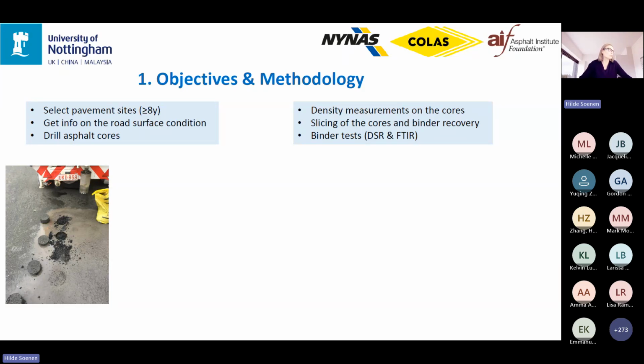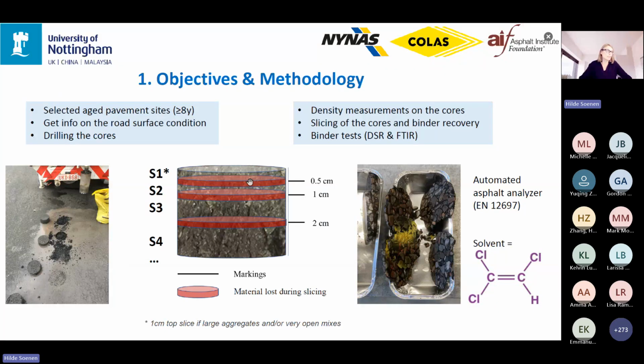Once we had enough cores, density measurements were conducted, nuclear density, which has the advantage that you get a density number every millimeter. After that, we sliced the cores. In this case, you can see we used very thin slices. First, we put markings on 0.5 centimeter, then on 1 centimeter, and then every centimeter. During the slicing, a lot of material gets lost. So you end up with very thin slices, and we needed at least 5 cores to get enough material after the binder recovery so that we could still do some tests.